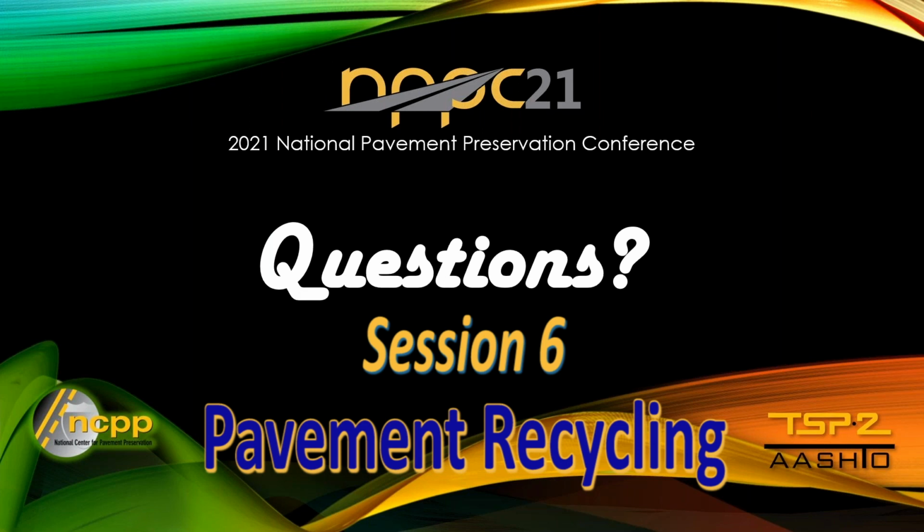Next question. Quick lime versus hydrated lime in CIR, what is recommended? Both of them are ultimately going to be a hydrated lime, but we recommend quick lime that you batch and then put in, because you can pump it into the water. The reason is you can use less. It gives you a little heat of hydration, and it's cheaper than trucking all the already hydrated lime. So we recommend quick lime that you essentially batch and hydrate on site and then put into the equipment.